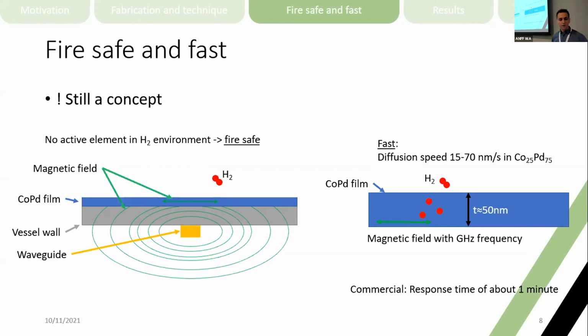And why do we think it's fast? Well, microwaves work in the gigahertz frequency range, so that's fast by itself. And the hydrogen diffusion speed in cobalt palladium is between 15 and 70 nanometers per second. And our typical thicknesses for our thin films is about 50 nanometers. So we should get a response within a few seconds. Compared to the commercial sensor, which I just said has a response time of about a minute.